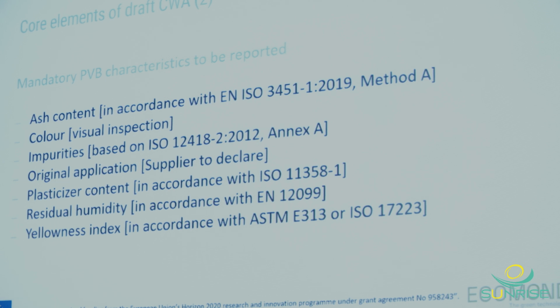So what are the mandatory PVB characteristics which we have included in that table? It's ash content in accordance to a specific EN ISO standard. Color, in this case only the visual inspection. Impurities, also based on a standard. Then the information on the original application, which obviously needs to be declared by the supplier. So for example, whether the PVB came out of windshields or out of building applications, and then also whether it's post-industrial or post-consumer, because that gives information about the possible degradation. Then the plasticizer content, the residual humidity, and the yellowness index.